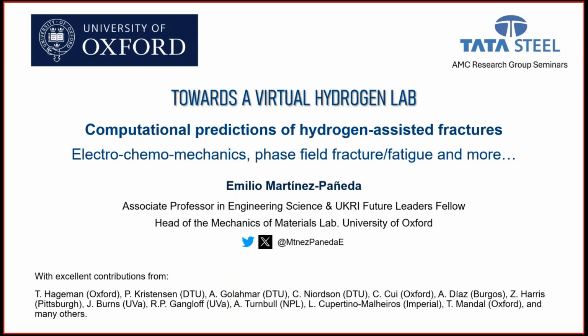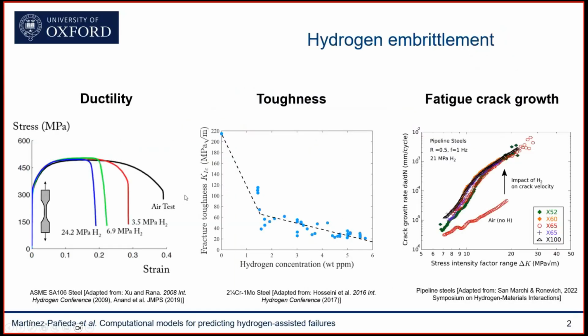So the motivation for the work is clear. There's significant interest in using hydrogen for decarbonizing many applications and sectors. But we know that storing and transporting hydrogen can be a challenge. We have known for a long time that hydrogen very significantly degrades metallic materials, and this has a significant impact on structural integrity. You can see some examples here on how hydrogen degrades the ductility of metals, their fracture toughness, and enhances the fatigue crack growth rates.